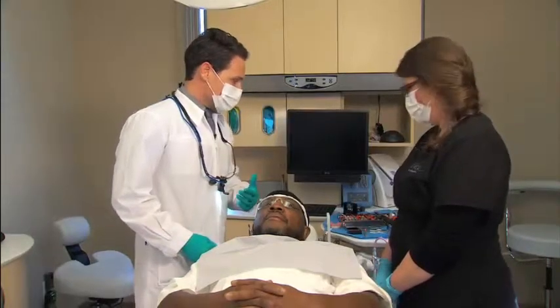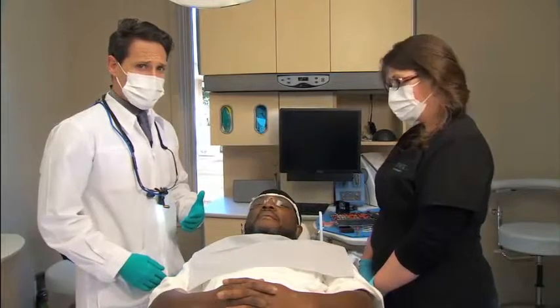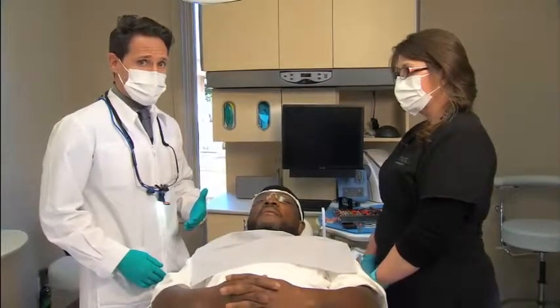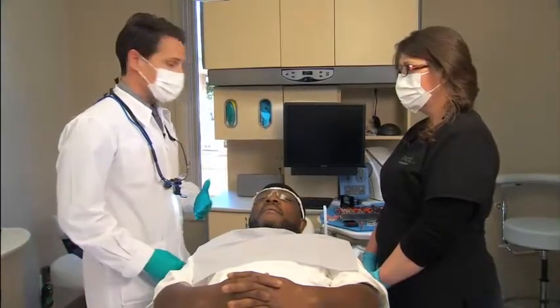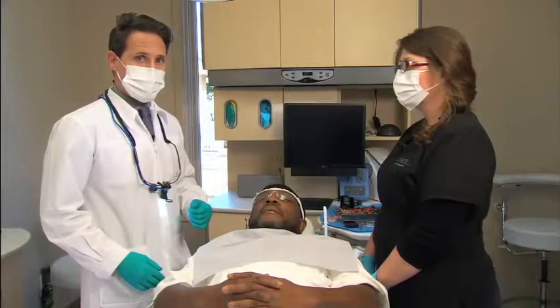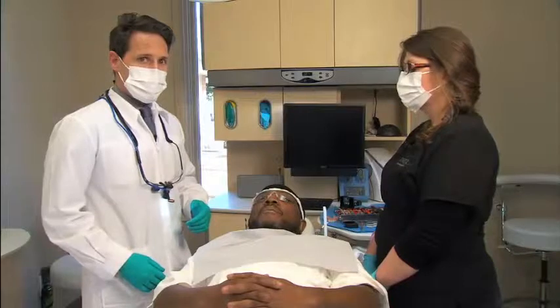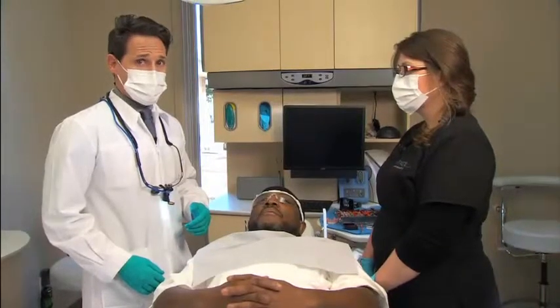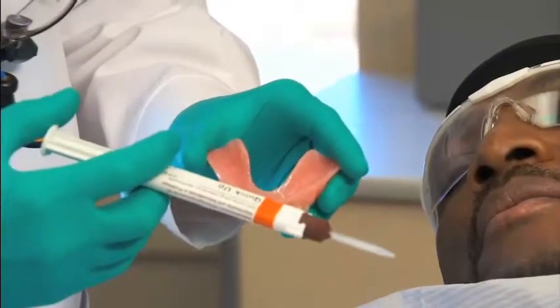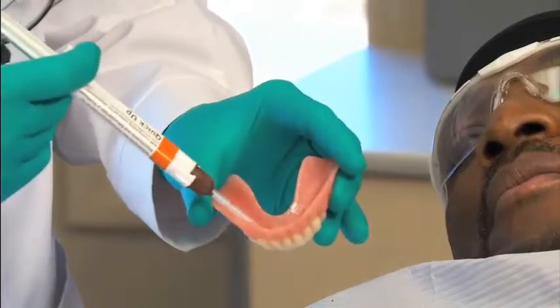And once again, like I was saying previously, we don't have a higher risk of the denture being locked on because of the method that the QuickUp self-curing composite is used. We're actually only going to fill up the reservoirs about two-thirds full and have Byron bite on that with gentle force, about 50%, and then that's going to set in 2.5 minutes. So it's definitely a very fast material. So as with the fit test, we really just want to fill this up about two-thirds full.